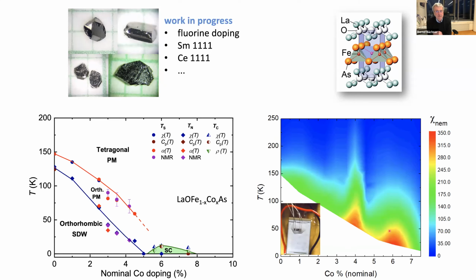And I did not show you everything. I showed you only, let's say, the strain derivative of the Seebeck effect, which is identical for barium 122 and for these systems. You can have a look at the Nernst effect. It's identical. You have this completely different system, structurally completely different, a lot of different properties, scattering completely different. One is a nice metal, the other is a lousy metal close to localization.